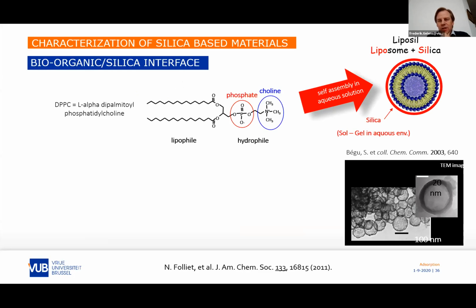So one of the proofs that there is a strong interaction with water is the following example. When you make some, let's say, little shells of silica using a surfactant, we have here a formation of what is called a liposome. It's a double layer cell, and around that again you can grow a silica, which forms liposyl structures, which is shown here.